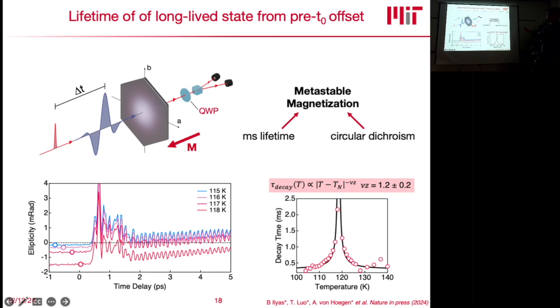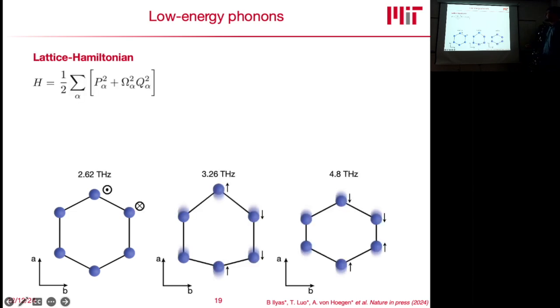So this gives us two ingredients that we can put together. We observe a millisecond lifetime, and we get this circular dichroism, which tells us that we're creating a metastable magnetization in this antiferromagnet that lives for a very long time. To make sense of this, we collaborated with the group of Angel Rubio in Hamburg. They initially calculated the low energy phonons to understand where this state comes from.